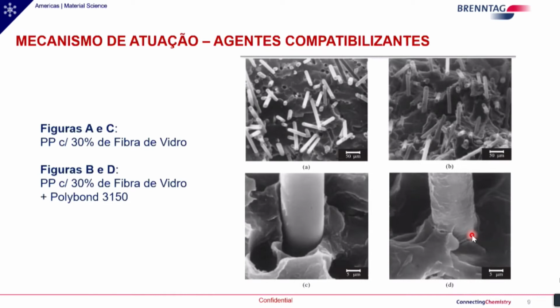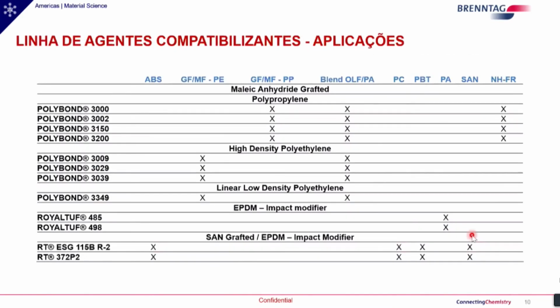Many companies currently use polypropylene with glass fibers, bamboo fibers, wood dust, or mineral loads without the use of compatibilizing agents, maybe because of a lack of knowledge, maybe because of a lack of analysis. But the mechanical properties are very much improved through the use of these agents. Here you see the line that Brenntag has available of these agents. It's a full line designed on the interaction between polypropylene and the mineral filler, or the mineral load, or glass fiber.